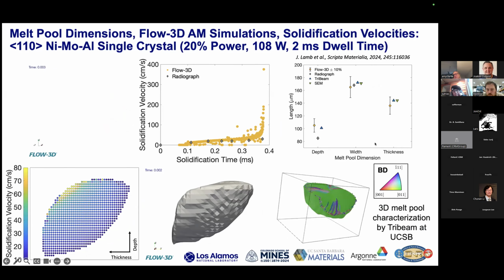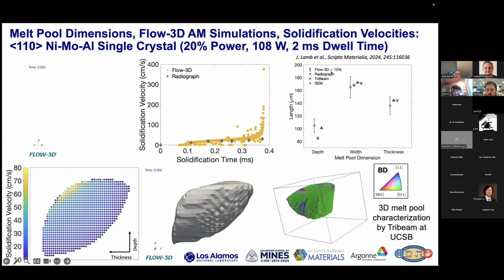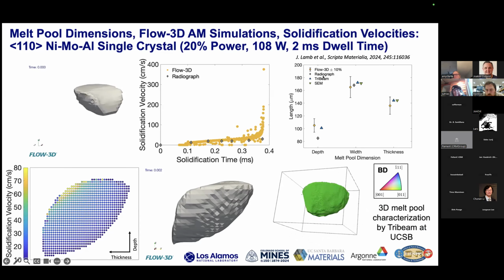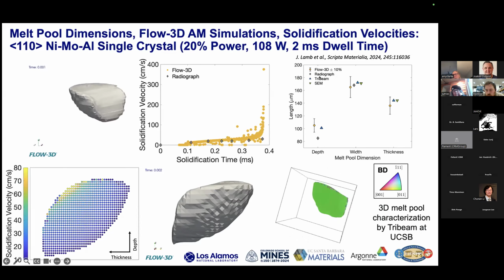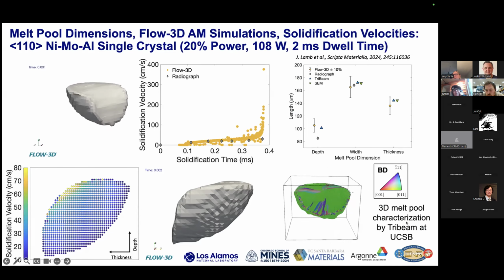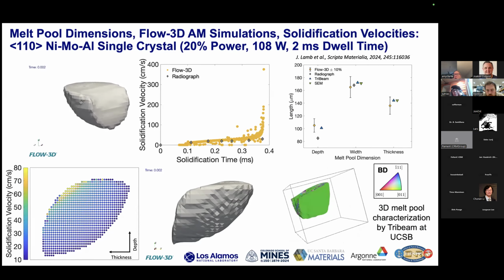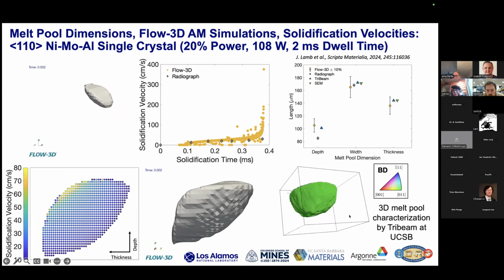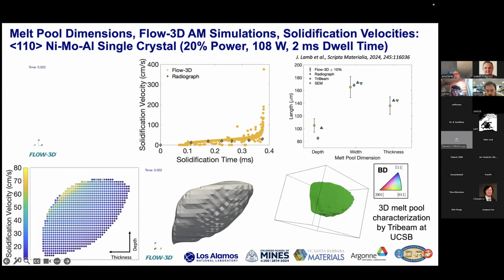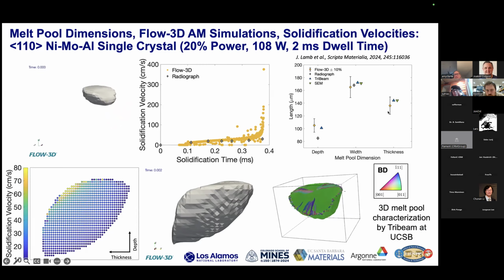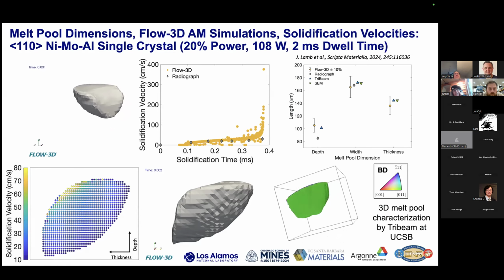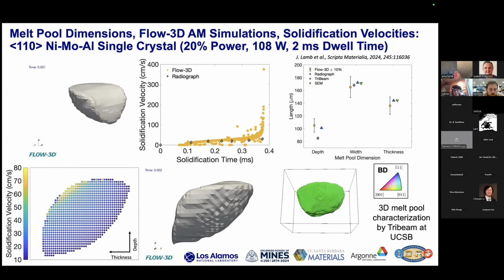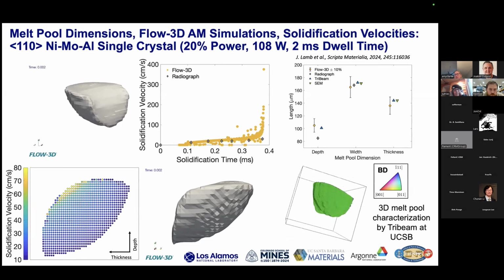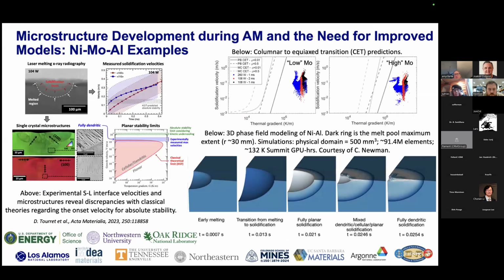And then we did some nice destructive characterization where we compared Flow 3D, radiography, destructive scanning electron microscopy, and also 3D tri-beam, which is a novel technique developed at UCSB that allows us to do 3D characterization of the melt pool. So an example data set is shown here for one of our spot melt conditions. And so now that we have the sense that we have fairly good matching across these techniques, we have the velocities sort of bound, we believe them. Now we feel better about the thermal conditions, so we can start moving forward to model microstructure development.